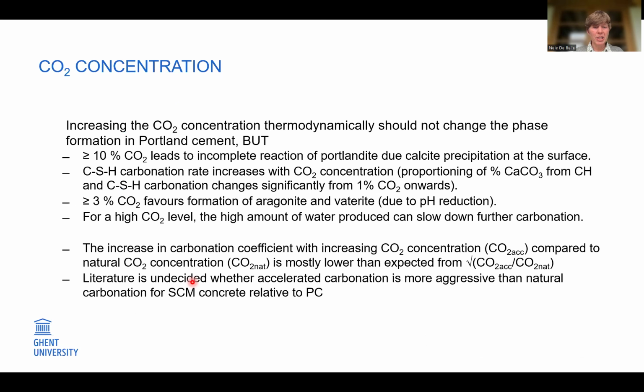What about CO2 concentration? Well, increasing this concentration is a common approach to accelerate carbonation for testing. And from a thermodynamic viewpoint, actually, it should not change the phase formation at all. But there are various side effects, as mentioned here. For instance, more than 10% CO2 would lead to an incomplete reaction of the Portlandite due to fast calcite precipitation at the surface. Also, CSH carbonation rate increases with CO2 concentration. So there would be more calcium carbonate formed from CSH versus Portlandite. So you have a change in proportions. And also the polymorphs found may be different at higher CO2 concentrations.